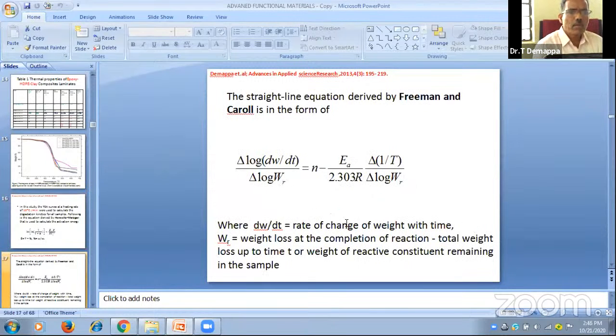This is another equation, the Freeman and Carroll equation, I told you. That is the delta logarithm of dW by dt, that means the degradation, or loss of weight, with respect to time. This is the weight loss at the completion of the reaction. We want the energy of activation E, and this is the order of the reaction. We plot a graph of this one on the y-axis and this one on the x-axis, then we get a straight line. The slope gives you the energy of activation, and the intercept gives you the order of the reaction.